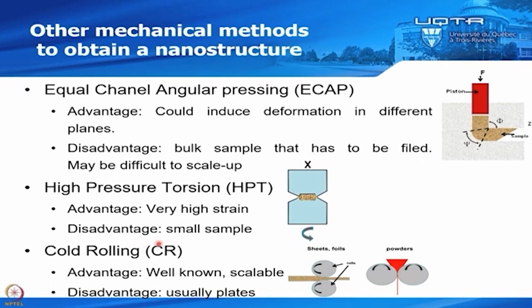And finally, we have cold rolling. So the advantage of that, it's a well-known technique, and I think it's very easy to scale because the industry is doing a lot of cold rolling. The disadvantage is usually you have to use a plate, but in our case, we solved this problem because we took the cold rolling machine and we rotated 90 degrees, so then we could process powder. Because usually our material, our metal hydride is in form of powder and not plate.